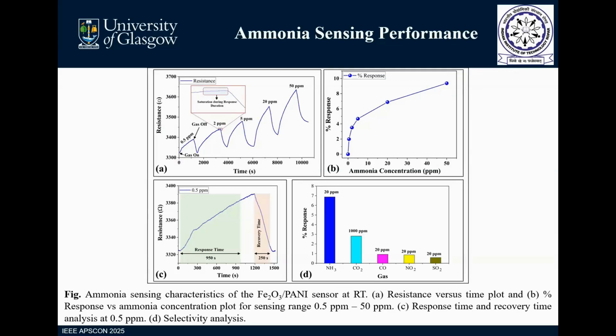Ammonia sensing performance was studied for 0.5 to 50 ppm of ammonia, and we can see that even 0.5 ppm, such a low level of ammonia, shows a response, with the resistance changing from 3.35 kilo ohm to 3.4 kilo ohm approximately. In figure B, we can see the corresponding response of the sensor, which generally lies between nearly 2% to 9% for 0.5 to 50 ppm of ammonia. Figure C is the zoomed version of the 0.5 ppm response, and here we can see how we calculated the response and recovery time. Response time is about 950 seconds and recovery is 250 seconds.